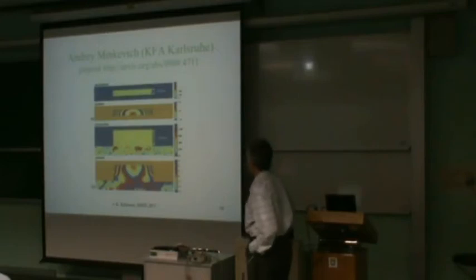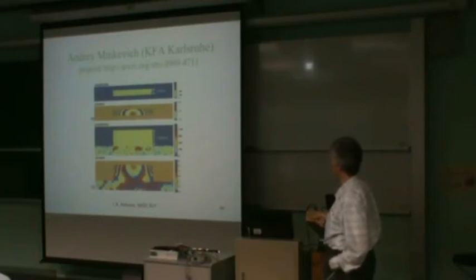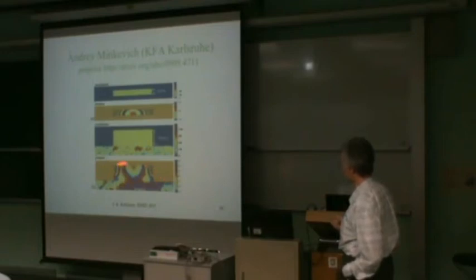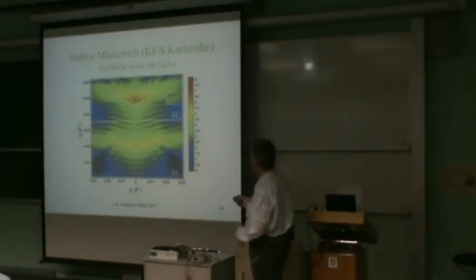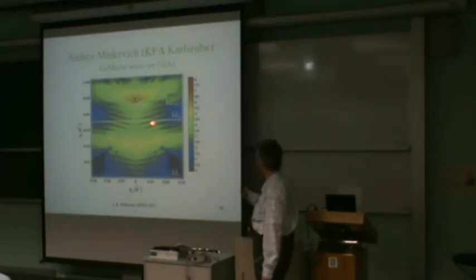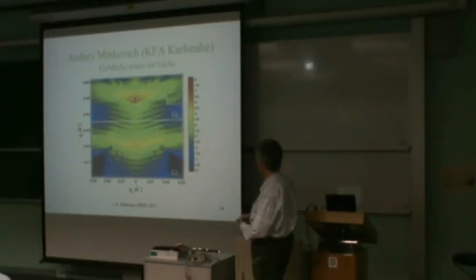So he came up with an algorithm, and he was able to get images of the strain pattern that's present in the overlay of the gallium manganese arsenide, and also a complementary strain pattern in the gallium arsenide underneath. And these strain patterns match each other fairly well. So you get separate images just simply by dividing the diffraction pattern, which has the 2 bright peaks. I think you just cut it at this line here, inverted this part and inverted that part, and got 2 matching images of the 2 pieces.